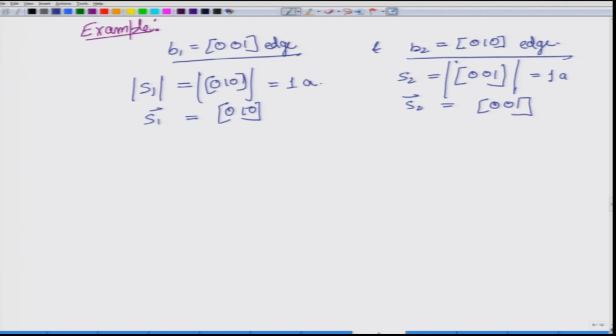Now, this is the direction, Burgers vector is this, these two are perpendicular, therefore, it will be an edge character. Here this is the direction, this is the Burgers vector, these are again perpendicular, therefore, this will also be an edge character. So, we do not need to know the line direction over here, just by looking at the two Burgers vectors we can say how it will look, and this is what we get in this particular one. We will try to solve some more examples the next time that we meet. So, we will end over here.